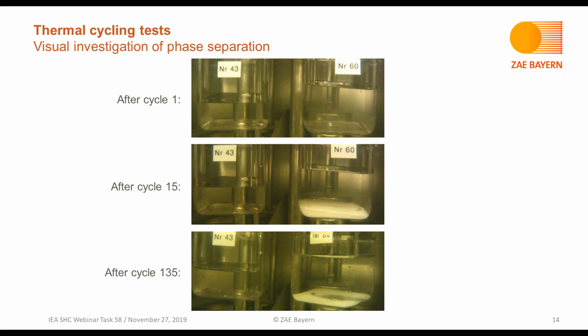At the top, you see the situation after the first cycle. So both samples shown here are completely in the liquid state as they should be. So this is the situation after cycle one at the high temperature. However, after cycle 15, you can see for sample number 60, there's some kind of solid material at the bottom, which indicates phase separation.